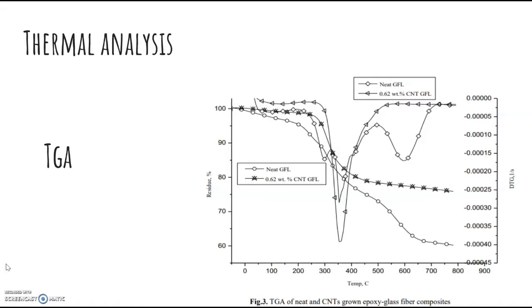The DTG plots also show weight loss peaks at 3 temperatures in the neat system. Multiple peaks were also found in the DTG plot of the neat glass system. Meanwhile, the peak degradation of CNT grown woven glass fiber composites was found at only 1 temperature, and this is 355. These observations indicate that the CNT grown woven glass fiber composite has a stable degradation at a reasonably higher temperature than the neat woven glass fiber composite.